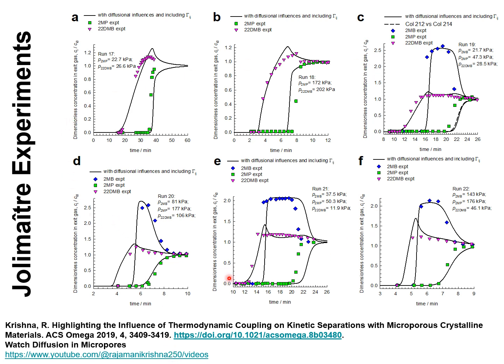The set of 6 experiments can be reproduced nearly quantitatively by a model in which due account is taken of the interplay between adsorption and diffusion using the Maxwell-Stefan diffusional formulation, and the predictions of the breakthroughs are shown here by the continuous black lines.